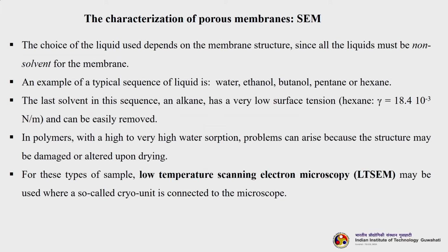And then the choice of the liquid also depends on the membrane structure, because all the liquids must be non-solvent for the membrane. Otherwise, if you use a solvent which is organic in nature, maybe alcohol or something like that, then it may swell the pores of the membrane, or swell the membrane, and the pore size will eventually increase, which you may not realize, but it will eventually happen.